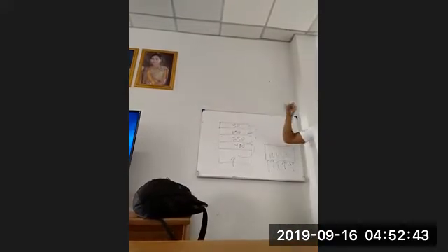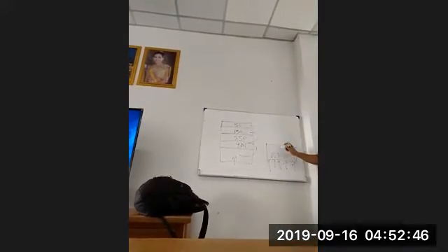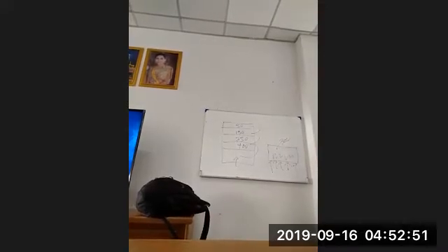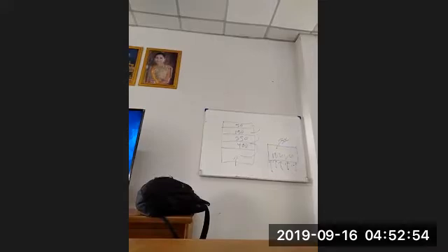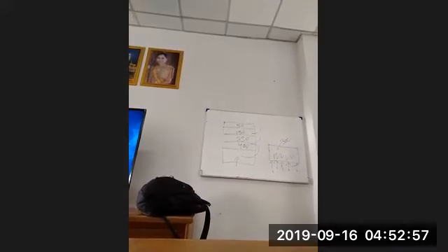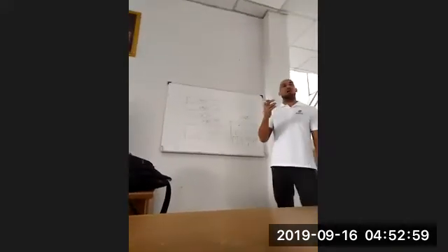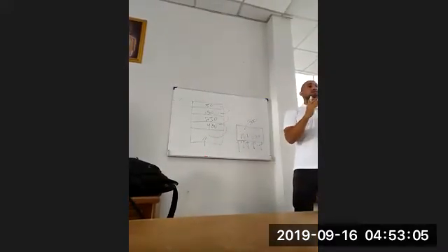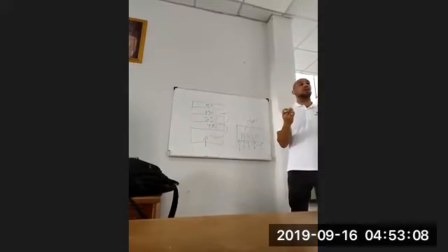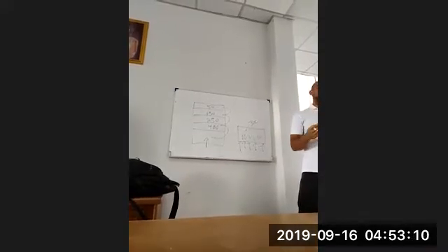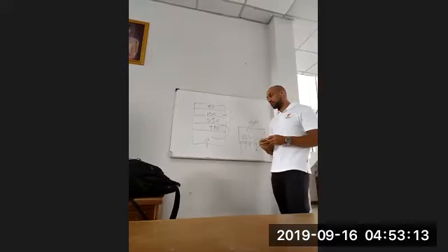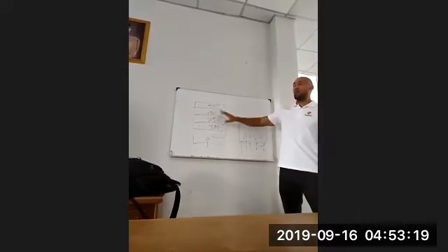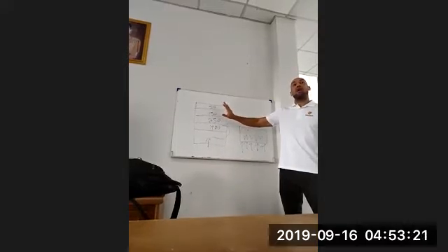Okay, so now I've addressed the issues that these guys have with their temperature at 300. They have a single temperature of 300 degrees and have to burn everything, and it doesn't do so evenly. We have the possibility of choosing different heat levels. Just as I'm talking about high density polyethylene, it can need to be broken down anywhere from 200 degrees all the way up to 400 degrees, depending on the recipe, depending on the producer of the plastic. The temperature we use depends on the recipe we're applying. So you have a couple of different things that this solves as far as problems go with pyrolysis.